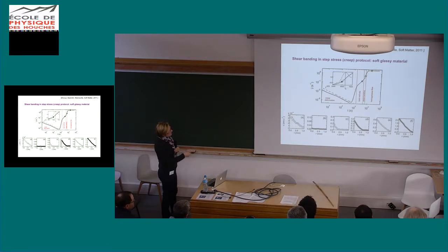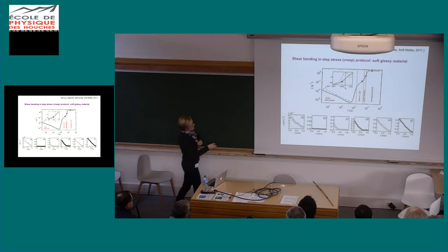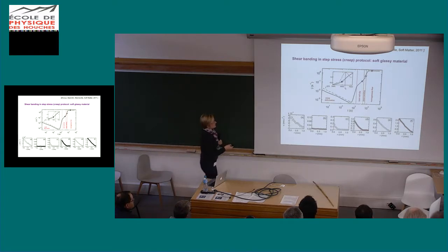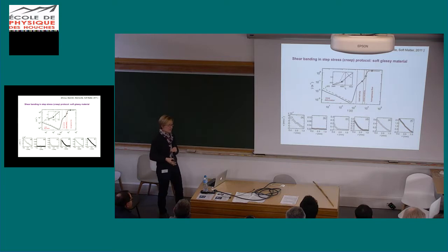Now, all kinds of complicated stuff happens as the sample yields, including total wall slip. And this is actually quite widespread across the experiments, and something that theory has done a very poor job of calculating so far. I mean, the vast majority of theoretical work simply assumes no slip at the wall. That's a really serious failing of where theory is at the moment compared to experiments.